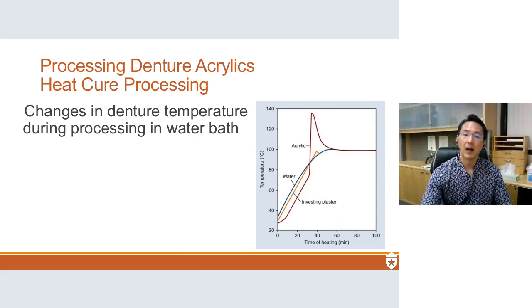So what we see here is, I hate this little bar that comes out. Anyway, as the water is heated up, okay, if it's heated up too quickly, you have the plaster following along, okay, and then the acrylic then follows. But because as it reacts, you have the exothermic reaction, the heat builds and it gets to almost 140 degrees Celsius. Okay? So that's why there is a monomer boil in that situation.